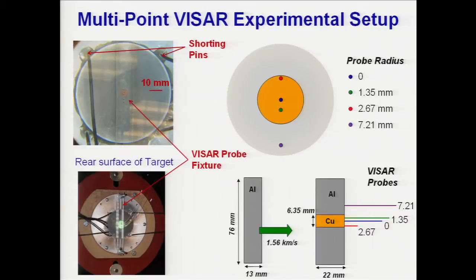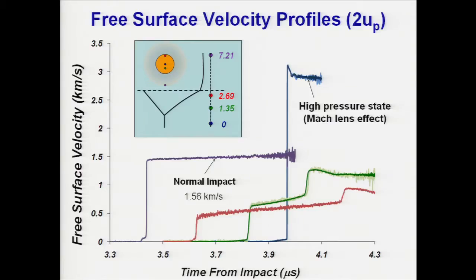So we measure this now experimentally. Here we show the velocity interferometer probes, the VISAR probes, which are used to measure the response at the back of the target. This is copper, whose properties we are interested in. We are impacting with aluminum at about 1.5 kilometers per second, and we measure the response at the back. These are the probes which are embedded here. These events are measured over a very short period of time. As I mentioned, the whole event lasts about a microsecond or so.